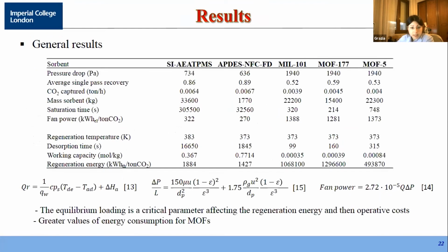Here we can see the general results, and we have two main important results that are the fan power and energy for regeneration. We can see that for amine functionalized sorbent, the fan power has an order of magnitude of about 300, while for metal organic frameworks, this parameter has an order of magnitude of about 1000.